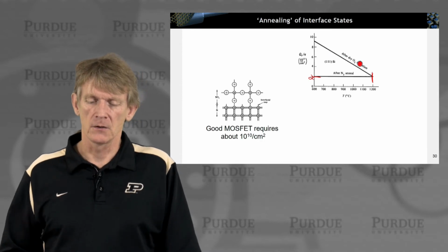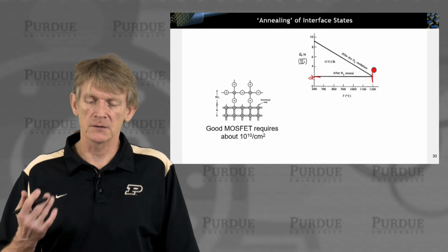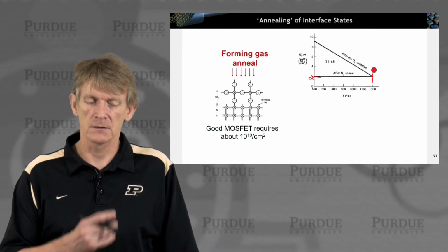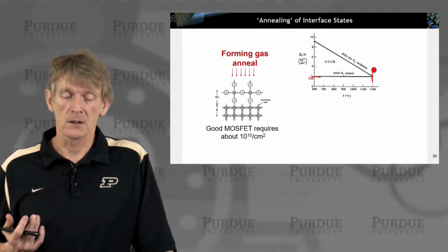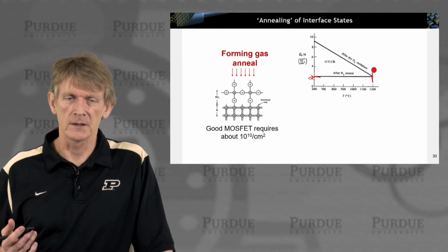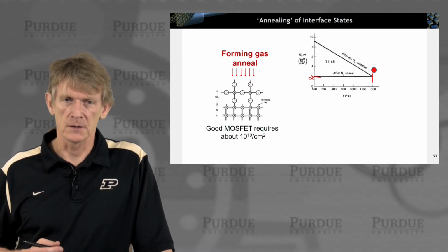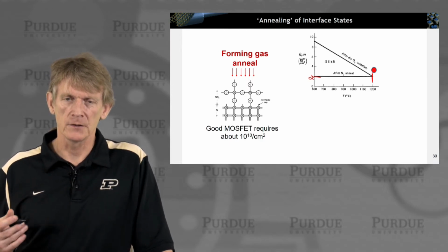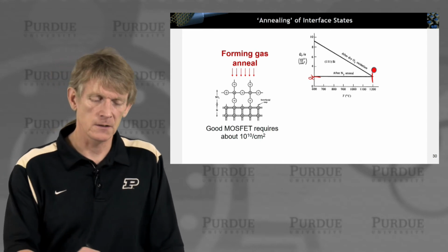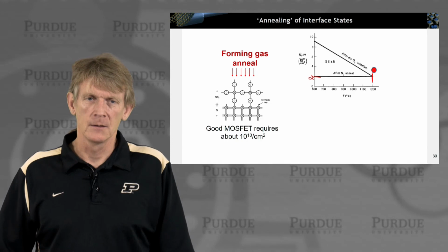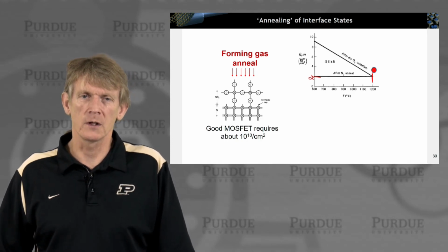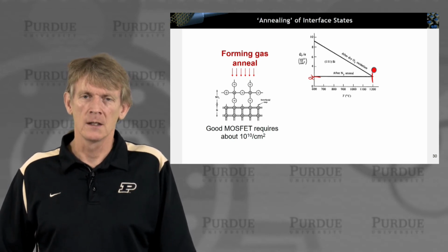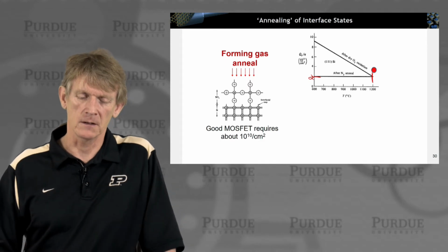Okay, so the point is, with just dry oxidation you'd have to have high temperatures, but you can also include nitrogen and basically reduce the processing temperatures. And why would you want to reduce processing temperature? Well, if you have really small structures, then not only the oxygen in the silicon dioxide moves around, but the overall structure underneath can move around as well. And if you have thinly grown layers, you might do damage there with too high a processing temperature.